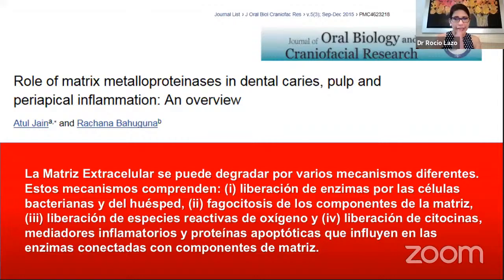Because in affected dentin, and in dentin generally, we have enzymatic proteins called metalloproteinases. The metalloproteinases are enzymes that cause degradation. They are in the dentin sleeping, but you can wake them up using an acid. If you are using a resin, in some cases you add orthophosphoric acid and you wake them up. You can tell me, Rocio, but I have universal adhesives or self-etch adhesives, but these have acids too. These acids wake up the metalloproteinases. That's the reason resins don't work well in affected dentin.